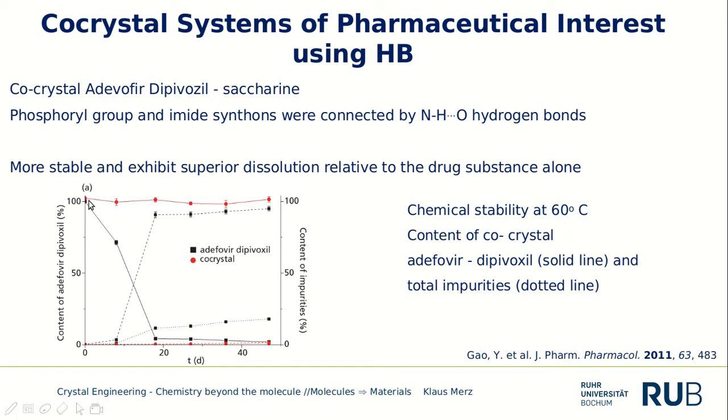In the case of the product alone, after only some days, mainly 10 days, you see a decomposition process start, and after 20 days it is nearly completely decomposed. Nearly no product, and a huge amount of decomposition products. Very nicely, you can use this pharmaceutical application to improve properties.